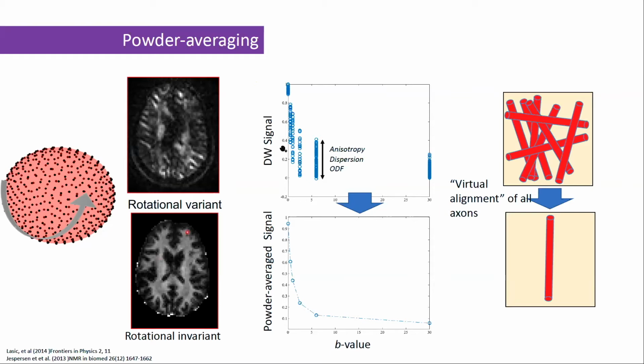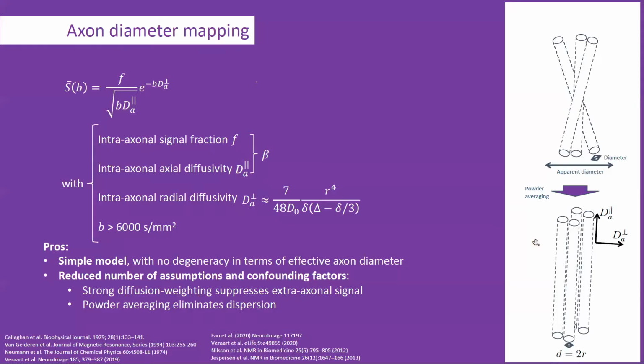the powder average signal. If we make a scatter plot between the B value and our diffusion weighted signal, we can see that per B value, we have a big spread. And that spread relates to anisotropy, dispersion, and the fiber ODF. However, we can just average that, and we get a simple signal decay as a function of the B value. And that simplification actually has big implications, because what happened by doing powder averaging, by averaging all the signal across different gradient directions per B value, is what you can call a virtual alignment of all the axons. So where the axons were initially dispersed with potentially different directions, they just virtually align. And that makes it so much easier to model this.